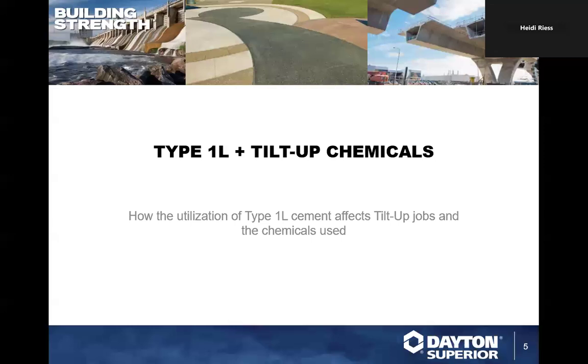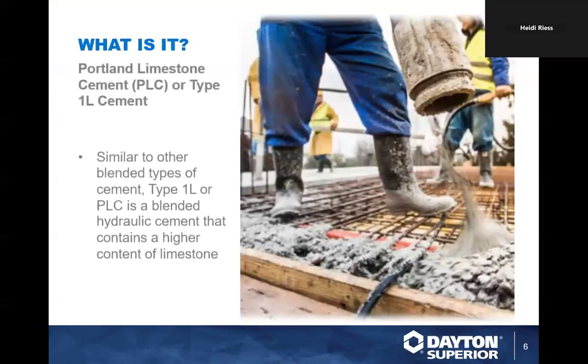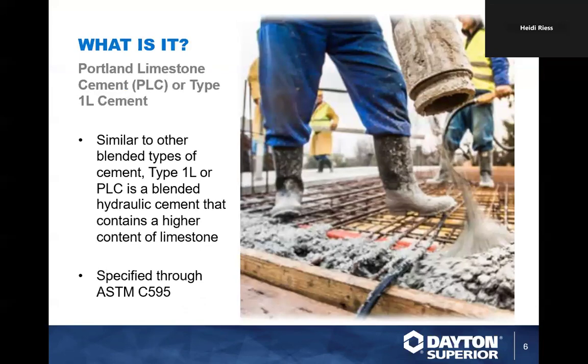Alrighty, thank you, Heidi. So we're going to go over type 1L cement very quickly, just as a brief refresher before we get into our main topic. If you'd like to learn more about it in depth, we have a previous Intro to Type 1L Training Tuesday that can be found under the Chemical Training webinar videos on our website under Related Trainings. So real quick, what is PLC or type 1L cement? It is a blended hydraulic cement that has a higher content of limestone, and it's specified through ASTM C595, which might be a new term. The types of cements we're used to working with in the past, such as type 1-2, type 3, OPC, are classified as just Portland cement and are specified under ASTM C150. So not only do we have a different category for PLC, but a whole different specification as well.